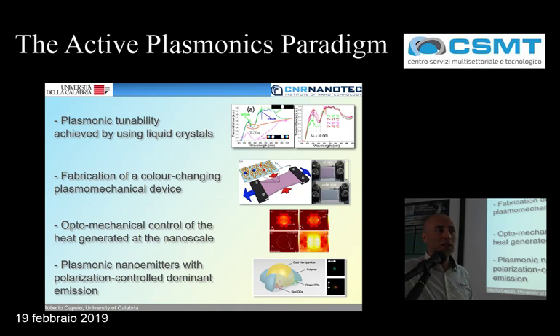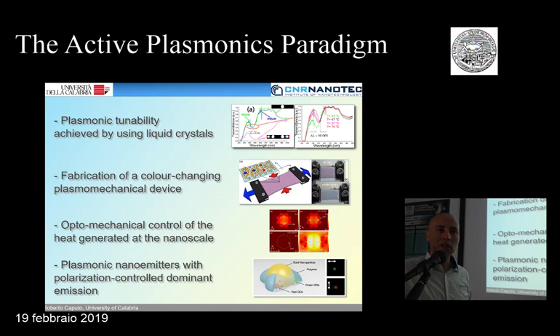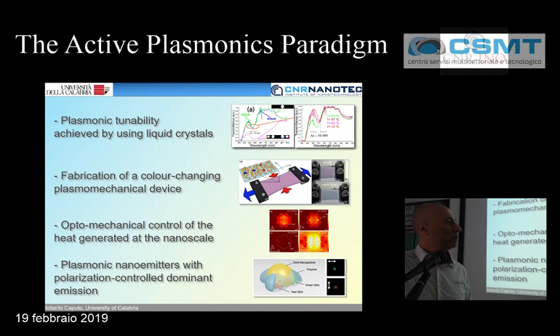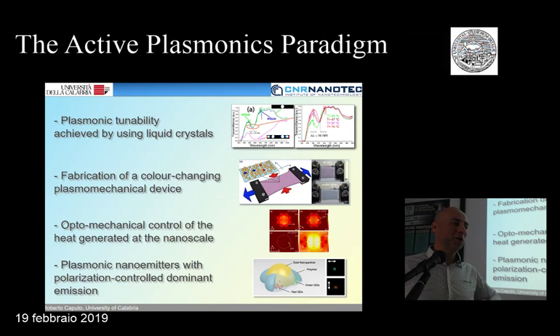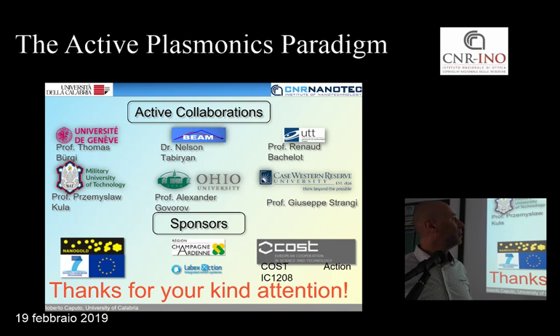And initially, this was just an idea to shift the resonance, but we started using this in a more fruitful way by just studying the thermal response of the system by changing the elastic reaction of the substrate. And finally, we showed these new possibilities for using plasmonics in a different way, but eventually very important at the nanoscale.